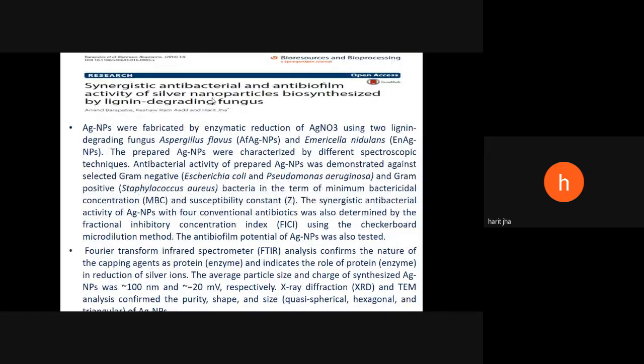This is again a work which was published in Resources in Bioprocessing. That is the synergistic antibacterial and antibiofilm activity of silver nanoparticles biosynthesized by lignin degrading fungus. In this work, silver nanoparticles were fabricated by enzymatic reduction of silver nitrate using two lignin degrading fungi, that is Aspergillus flavus and Emericella nidulans. The prepared silver nanoparticles were characterized by different spectroscopic techniques.